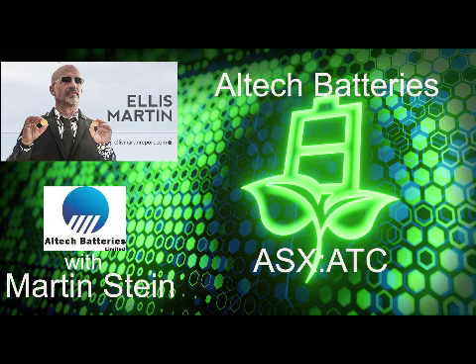One of the problems we've seen over the years is retention of battery life and capacity. Will this process using the alumina help mitigate that? That's correct. It is the first cycle loss that's an issue, and graphite has it as well. Graphite loses about 10%, but silicon loses so much more because of its reactiveness — uncoated silicon actually loses about 50% on the first cycle loss. Our coating technology is encapsulating the silicon and stopping that first cycle loss from occurring.